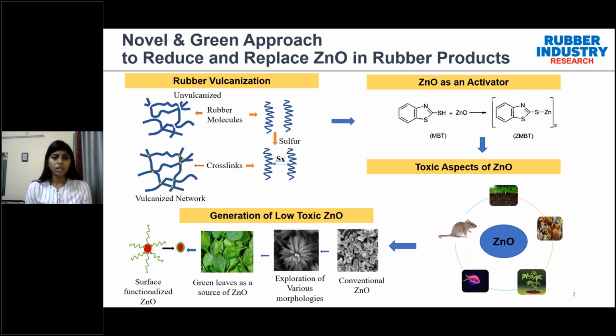We know that 50% of the global consumption of zinc oxide goes to the rubber industry alone. A recent study conducted by Swedish and British researchers shows that about 150 tons of zinc is leaching out from tires every year. This high release of zinc into the environment is toxic to aquatic species, microorganisms, and algae. So owing to these ecological concerns, minimization of the zinc oxide amount in rubber compounds is a necessity.